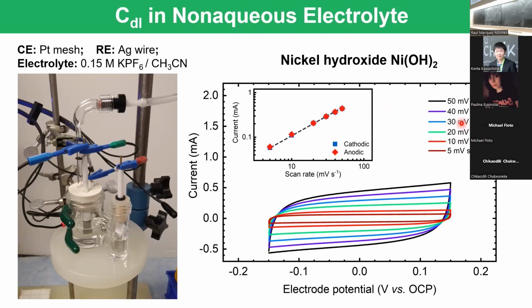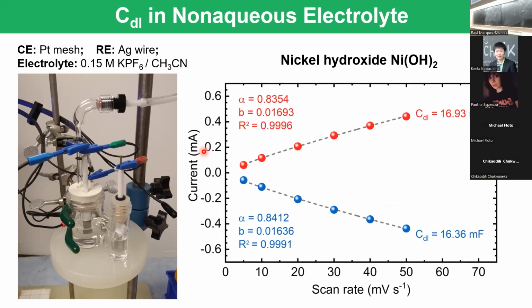But it turns out that, as I explained, one common issue is that if the material is not conductive, you may have some overestimations. Because notice here the units, milliamps. So this is really high. And if we look for the double layer capacitance, we get a really high value. And this large value is just because, and also noting the exponent here is 0.8, so it's getting smaller. And this is because nickel hydroxide is not a good conductor compared to metals, of course.